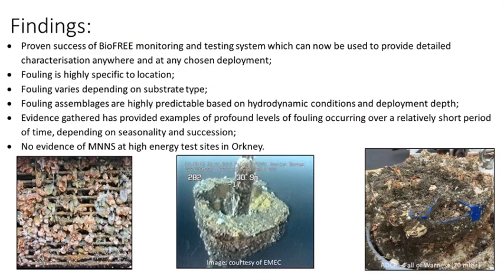We found that the monitoring and testing system is proven successful. It has survived in these very difficult conditions, so we're very, very happy about that. We have found that fouling is highly specific based on location and also based on substrate type, and that these assemblages are highly predictable based on hydrodynamic conditions and deployment depth. Using that buoy, as I mentioned in the example earlier, you can get profound amounts of fouling occurring in a very short period of time.